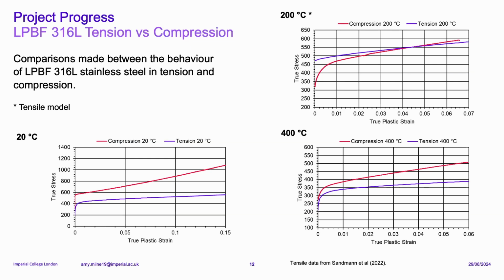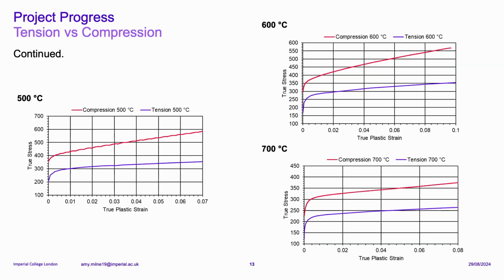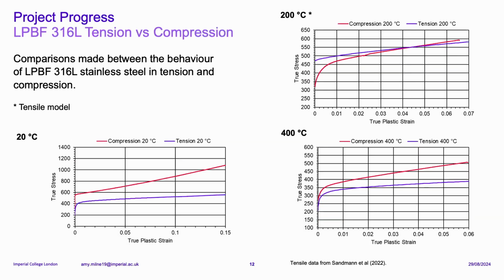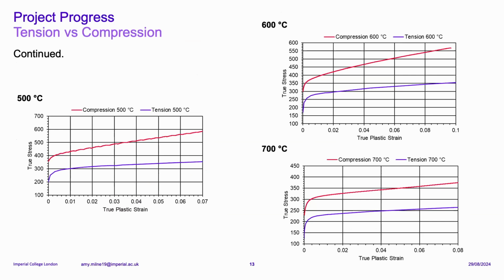So you can see in most of these on both slides, the compressive yield strength is higher than the tensile yield strength, with the exception of 200, which came from a tensile model, which we think is quite unreliable for the early plastic strains. But for the rest of them, it does line up with the expectation that the material will perform better in compression. You can also see that the curves begin to deviate further apart at higher temperatures. The reason for this could potentially be some stress relaxation occurring, because the samples were held at temperature for an hour before the test occurred.